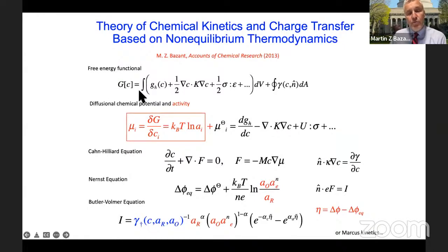The way to do the modeling is you start out by writing down a free energy functional for the system as a function of the various internal variables, such as, for example, the concentration. So here's an example to model those particles I showed before, where we have an integral over the volume of the homogeneous free energy, G_H, that's, for example, that double well function I showed you before, and then a bunch of other terms. The next term is the so-called gradient penalty or gradient energy, and what it does is basically assign a certain energy wherever there's a sharp change in concentration.